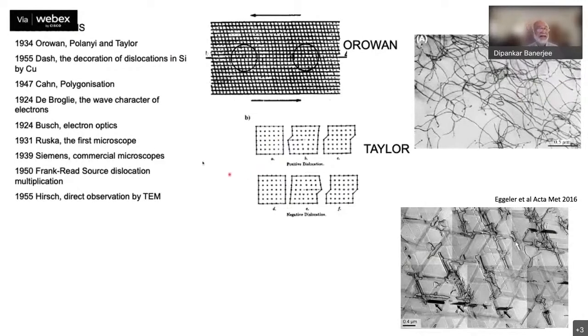The other part of this paradigm is our understanding of how defects in materials interact with the material structure as I described it in the previous slide, to provide the two aspects of metals and alloys that we are interested in application. One is the toughness or plasticity in the material, which is actually achieved by the motion of these defects that are called dislocations in the material, imaged here at transmission electron microscope, and the restriction of the motion of these dislocations in multi-phase materials to constrain the motion of the dislocations, as you see in this slide, provides strength in the material. So this interaction between defect structure and microstructure to determine properties is a key element of structural materials.